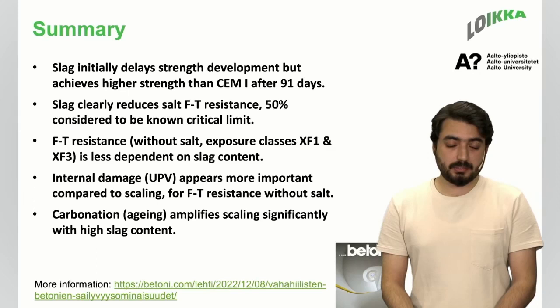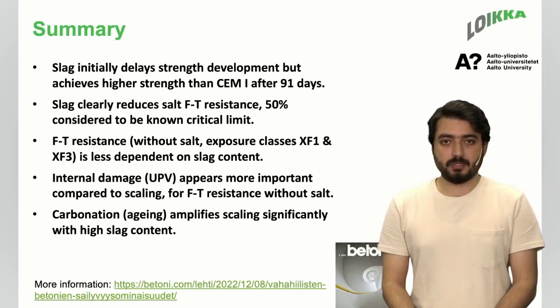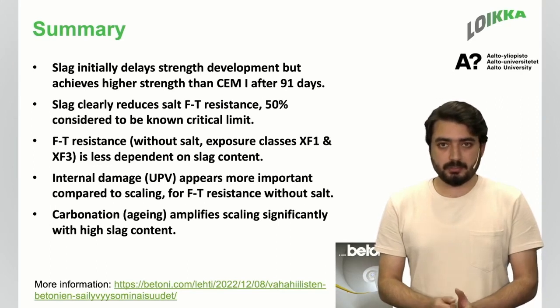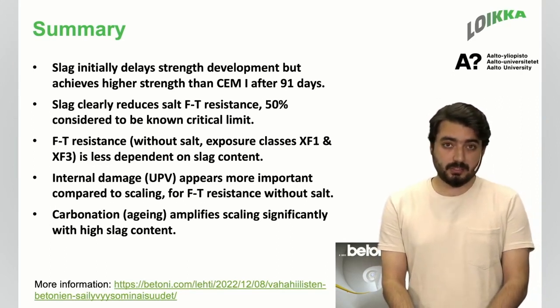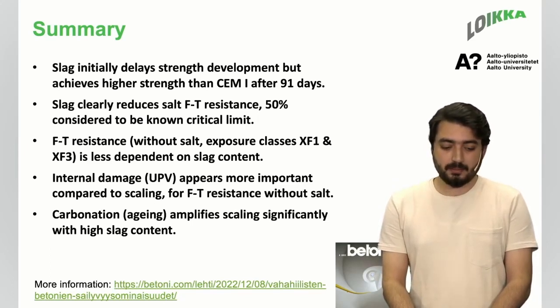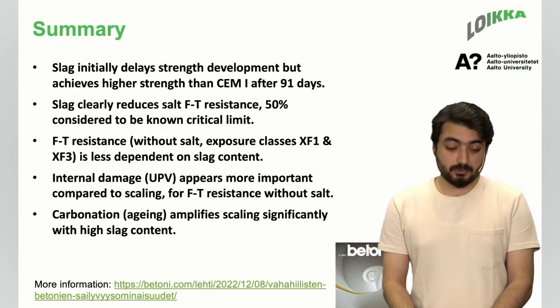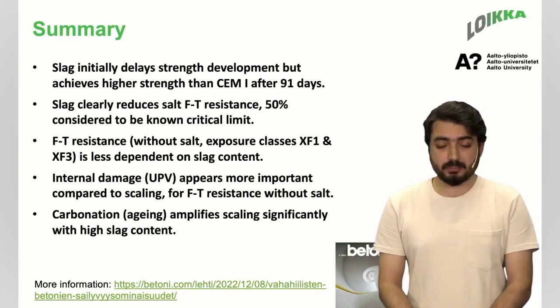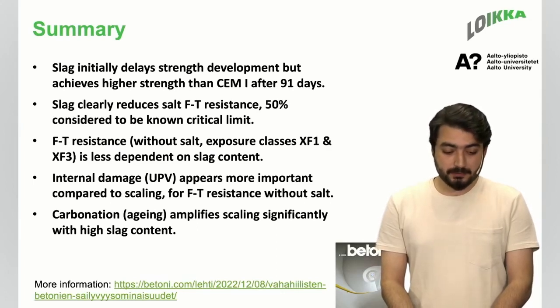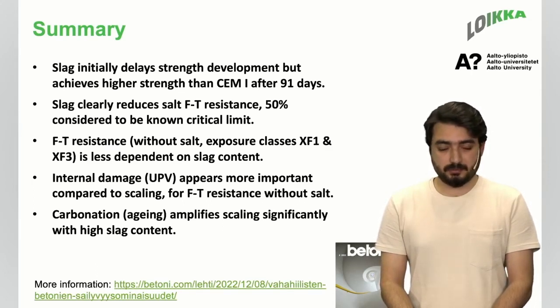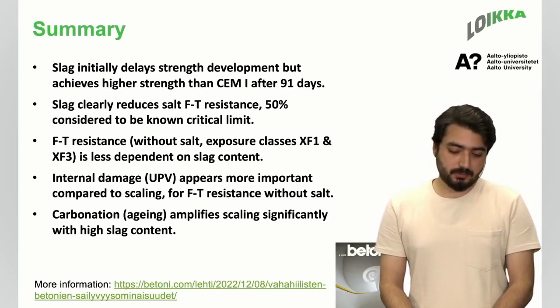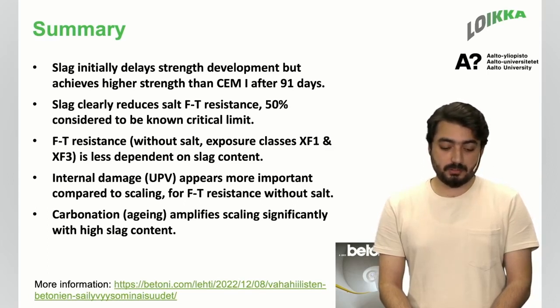Freeze and thaw resistance without salt, especially for exposure class XF1 and XF3, was dependent but quite less. It had a really low effect on the freezing and thawing due to the increase of slag content. Internal damage, which we measured via UPV, appeared to be a more important parameter than scaling in the case of freezing and thawing resistance without salt water. Lastly, carbonation or aging amplified the scaling significantly when the slag content was quite high. So that was basically an overview of all the work in a really short time.